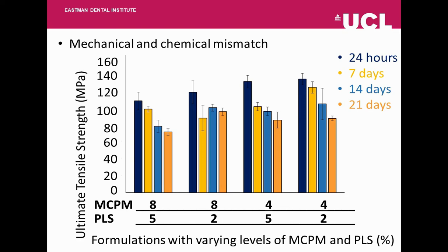We can see from the graph, after 1 month, the tensile strength decreases in all the groups, and also increasing levels of monocalcium phosphate and polylysine decrease the tensile strength overall. Getting the right proportion of monocalcium phosphate and polylysine is important. We want to make sure the material's tensile strength is optimum to prevent fractures post-surgery.